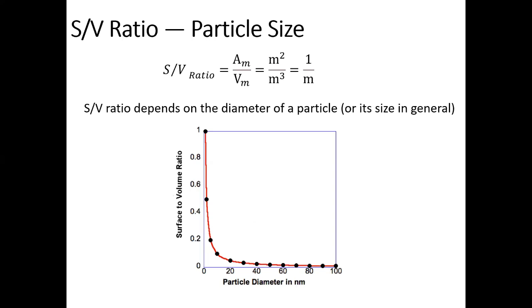I mentioned briefly yesterday that we looked at the optical properties of gold that we fabricated inside these pore channels. Some of them were very long cylinders, some were spherical particles, others were flat pancakes. And I said all of them were different colors. Remember that? That's an absolute proof that size and shape matter. And it does matter in nanomaterials. That's what makes nanomaterials so good.